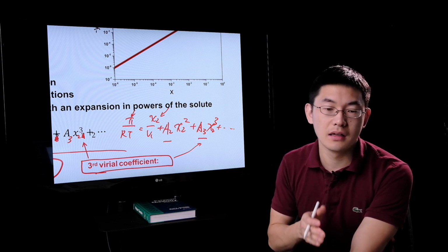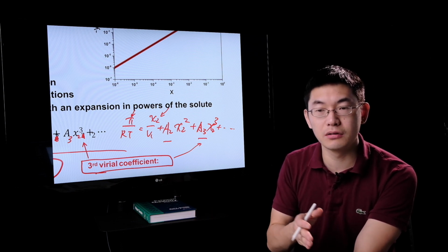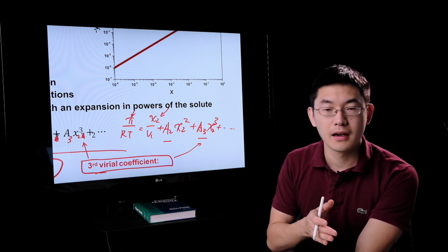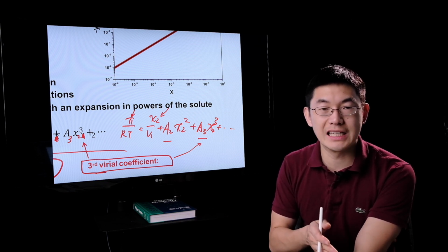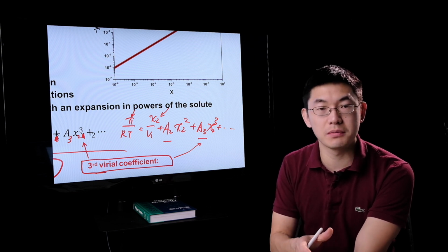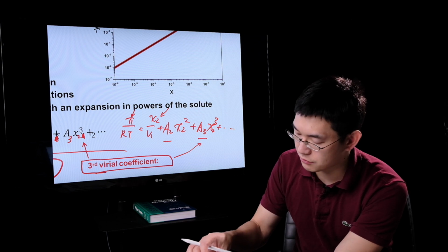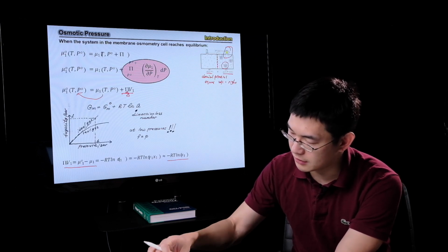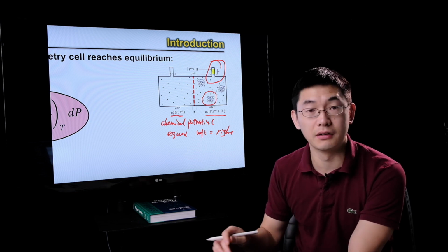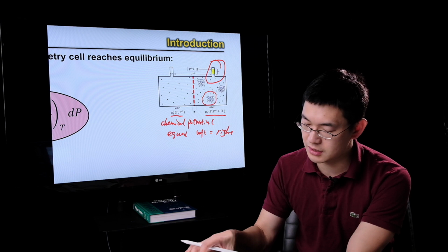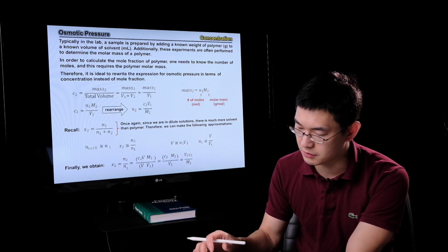So let's say I made 1 mg per mL, and 2, and 3, and 10. Then I measure the osmotic pressure, the pressure present inside each particular concentration. And you measure pressure by measuring how much the liquid rises in a capillary tube, as shown at top right here. Nowadays, this is a very old way, and modern instruments can measure osmotic pressure for you.